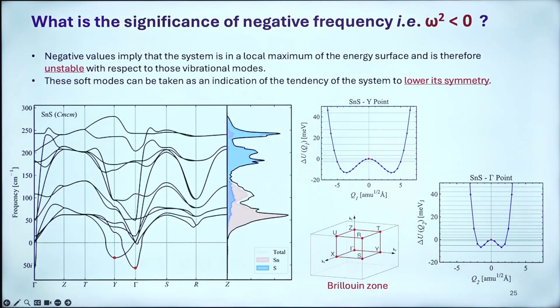Now, what is the origin of negative frequencies? That is an interesting question. This is for tin sulfide in the orthorhombic structure. We do see a phonon mode which becomes imaginary along the Y point and the gamma point. These two are of interest to us. When you try to distort this mode as a function of amplitude and compute the energy, you get a double well like thing, for the Y point and the gamma point. Subsequently, when you freeze this particular mode and do the distortion, it will eventually lead to a new space group, which will be ferroelectric. This Cmcm phase group is paraelectric and non-polar,